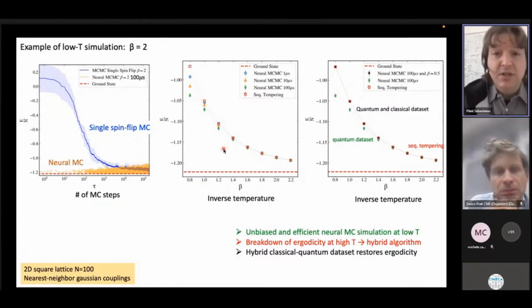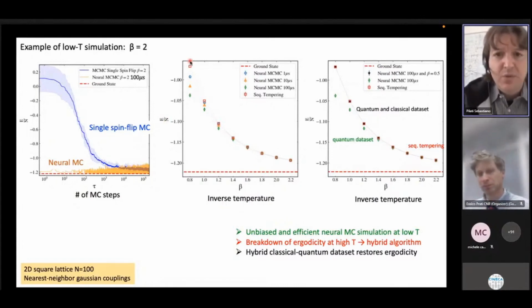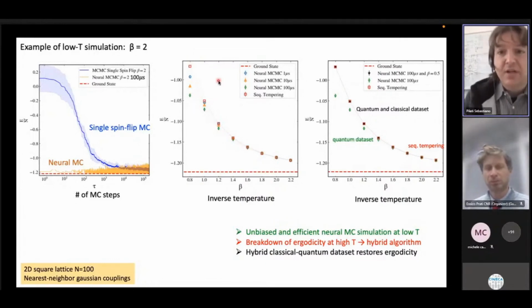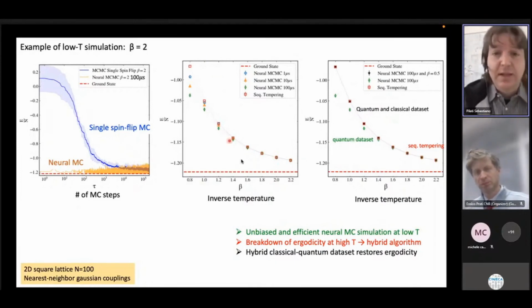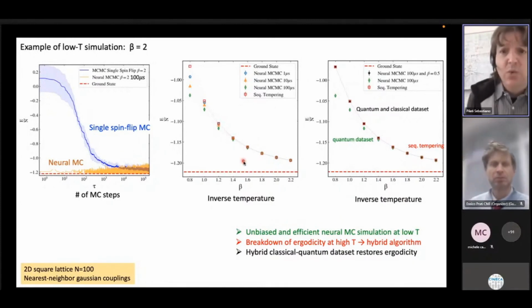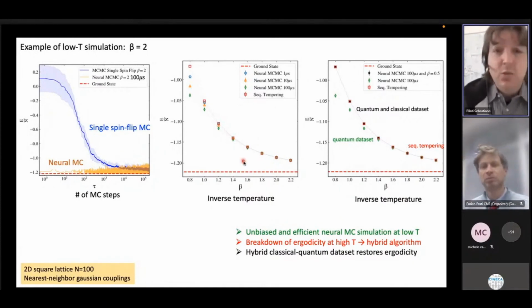And what is interesting is this plot in the middle, where we have the energy as a function of inverse temperature, and in red you have the exact results that we obtain with this sequential tempering. And with the different colors, you see different types of neural Monte Carlo simulation where the neural network was trained on D-Wave data. And you see that in the interesting regime, the low temperature regime, which is on the right, we get unbiased results. Of course, we see some problem at high temperature on the left because the D-Wave data do not span the high energy sector.